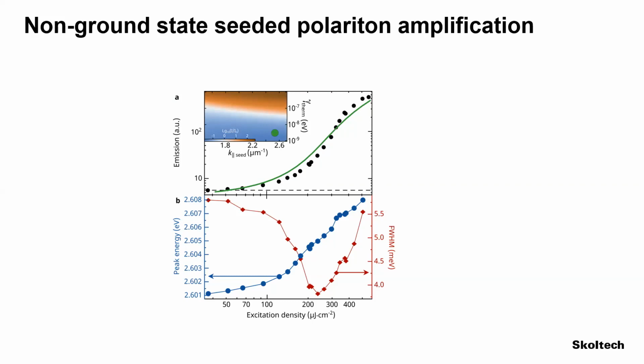This is the blue area of this phase map. We are operating here at the green dot. And indeed, what we could see is that we can amplify the seed from a non-ground state and get the line width narrowing, the energy shift, and the nonlinear emission that we saw from polariton condensation or polariton amplification from the ground state. So if I put this together, it tells you the following.